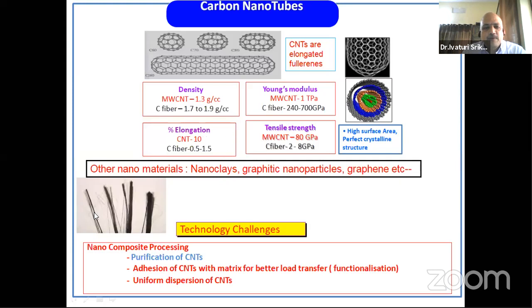Then elongation. Carbon fibers, as we have seen here, are brittle. They are not like metals, which are ductile. These carbon fibers are brittle with very low elongation. Nanotubes have a very high degree of elongation. So this has attracted the composite fraternity. What the composite fraternity thought was, if we can tap the potential of nanotubes as a reinforcement in place of carbon fiber, even if you use 10% or 20% of the total strength of nanotube, you will end up with a composite of around 8 to 16 GPa, against the 2 GPa strength composites that we see today. So that was the motivation for research in the area of carbon nanomaterials, especially carbon nanotubes.